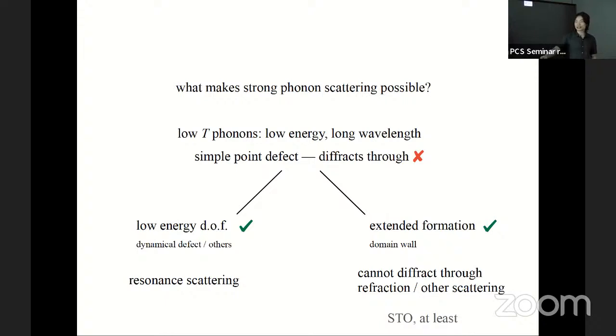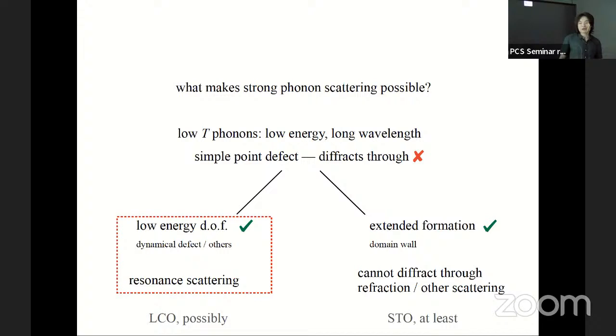And at least in STO, we saw that there's a domain wall. Actually, in STO, we need both, but the main thing is the domain wall. We know that in LCO, there should be no structural domain wall. So we try to explore this possibility: maybe there's some low energy degree of freedom where resonance scattering occurs. Then maybe that's a possible explanation for LCO. Even if it's not the mechanism for LCO, in principle it's some mechanism that is worth exploring in general.